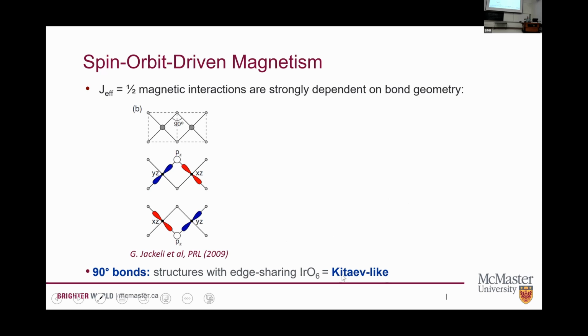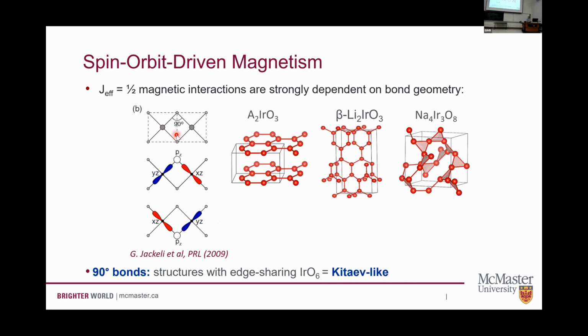If we change the geometry, though, if we go from these corner-sharing octahedra to edge-sharing octahedra, like this, then something very different happens. Now there's 2 exchange pathways here, one running through this upper oxygen, one running through this lower oxygen, and you can get destructive interference between these 2 superexchange pathways. And so that causes that normal Heisenberg interaction to cancel out or vanish. And what we get in its place is what's known as a Kitaev interaction. This is a geometry that we see in honeycomb lattice type materials, or different versions of 3-dimensional honeycomb shapes. This is called a hyper honeycomb lattice. This is a hyper kagome lattice.